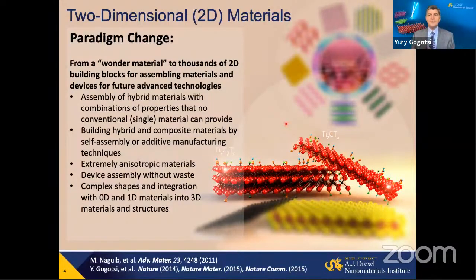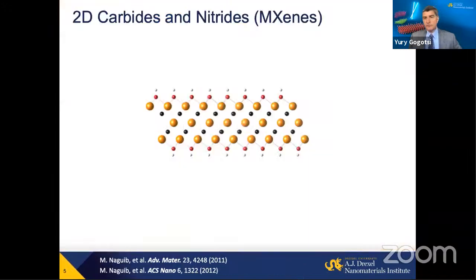Moreover, we need for this naturally dielectric, semiconducting materials, and metallic materials. We need materials with different surface chemistries, with different properties. So that's extremely important because we can make anisotropic structures. We can design and produce devices without waste, just simply by assembling them, chemical assembly, self-assembly. And of course, we can also assemble 2D sheets with zero- or one-dimensional materials. But one thing is important here. 2D sheets can be assembled in a very dense way, producing something looking like a perfect structure, like, again, bricks in the wall, without gaps, with a high density. And that's actually important for many applications.